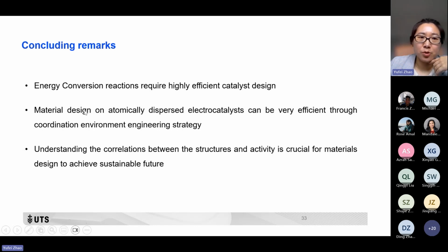And also for the material design strategies for these atomically dispersed electrocatalysts, we can see the coordination environment engineering strategy is quite important to modify the electronic structure of the center metals, and then for the high performance of the energy conversion reactions. And the third one is the correlation between the structures and activity. Currently, it is also very important. We now use in situ characterizations to monitor the dynamic change during the electrocatalytic process. So except for only characterizing our materials, we can know more details about how the material will change under this kind of electrocatalytic process, and then understand more about the materials and the dynamic process.